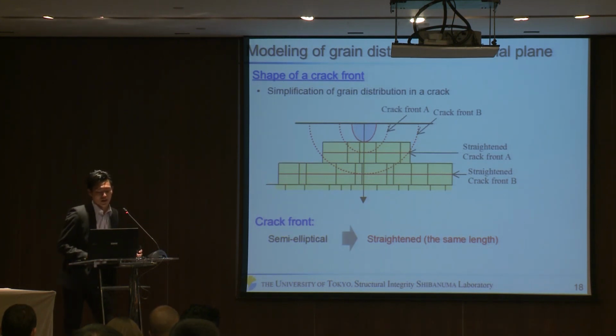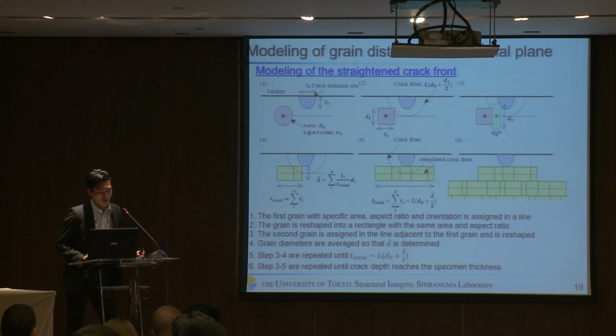Crack fronts are assumed as a straightened line with the same length as that of the semi-elliptical lines. So the semi-elliptical lines are changed into a straightened line. And this is the procedure of microstructure modeling. First, a grain with specific area, aspect ratio and orientation is assigned in a line, and the grain is reshaped into a rectangle with the same area and aspect ratio. Second, the next grain is assigned in the same way and reshaped, and the grain diameters are averaged so that this equation is met.